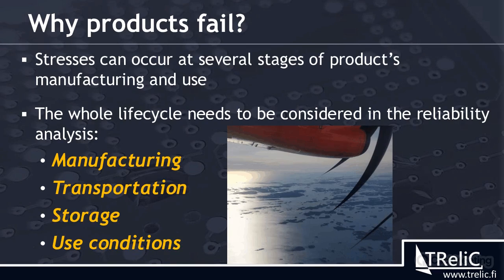In addition, we have, for example, transportation almost always. In this case, it's often mechanical stresses due to, for example, vibration, but also temperature, humidity, impurities, and so on. And then we can have storage. For example, at the moment, we have one project where we have issues caused by storage conditions which have caused corrosion.